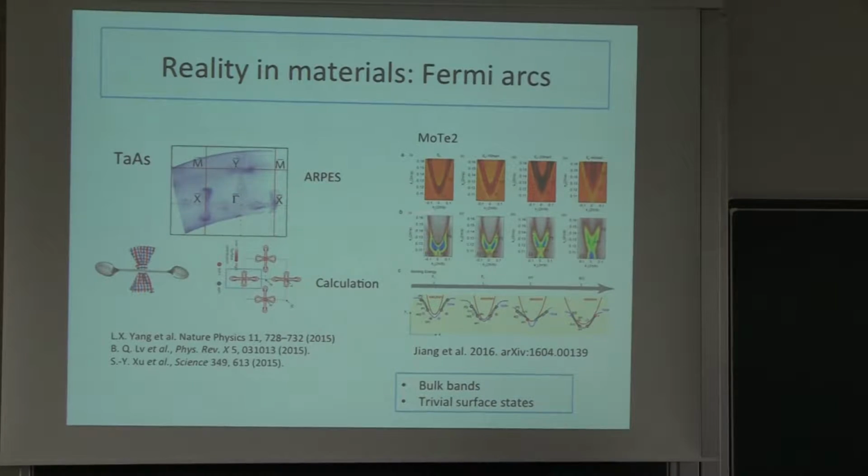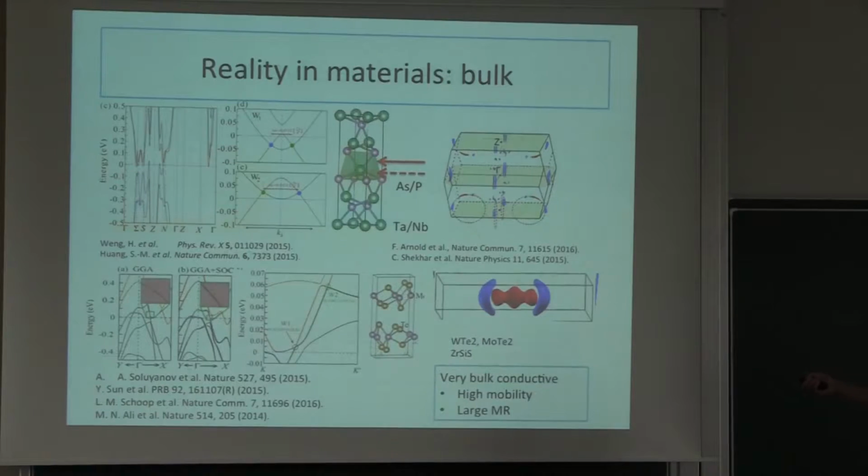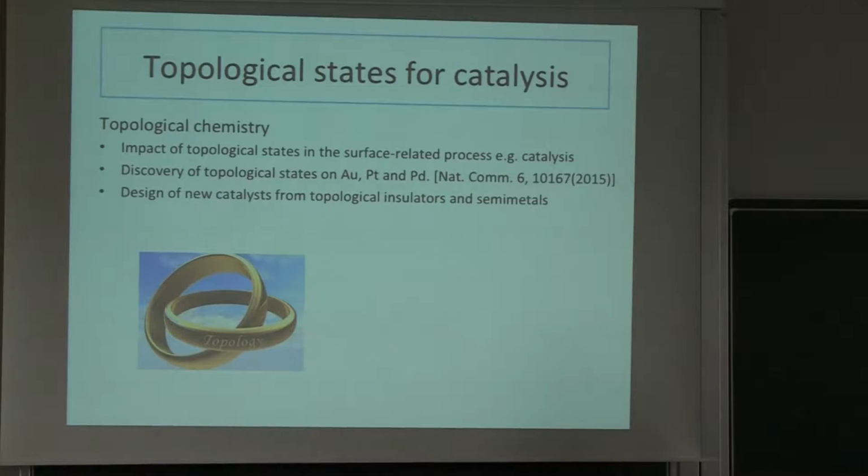And this is a type 2, the photoemission is the same. This is surface states, but with the surface states, we also see there are trivial surface states. At the same time, they are mixed with the bulk bands. And since we talk about this being a topological semi-metal, usually we assume the band structure is as simple as this one. However, this is reality. Reality always gives you such a complicated one. Here we already assume there are no defects and no other things, and it's already very problematic.